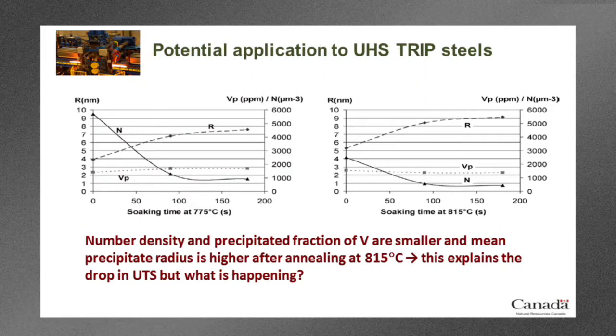On this slide here, we've actually tried to quantify the precipitation state as a function of the soaking time at the intercritical annealing temperature. And we did this at two different temperatures. We did it at 775 Celsius and we did it at 815 degrees Celsius. Now, if you remember, the mechanical properties at these two temperatures were quite different. We had quite a lot of softening in the ultimate tensile strength at the higher intercritical annealing temperature. These graphs can help to explain that.